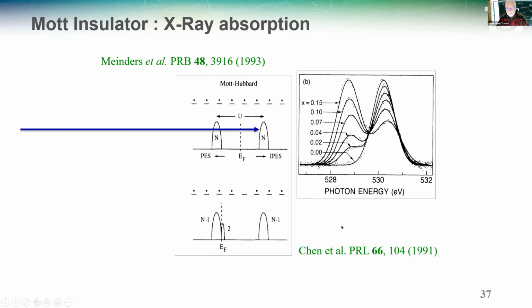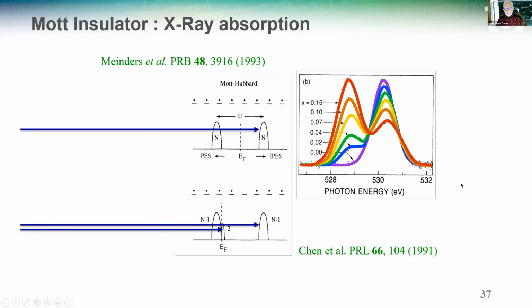So let's go back to the experiment. If I send again my high energy photon, you see that this peak has decreased in intensity. And now you have another peak that grows here. At 2% hole doping, there's a peak that grows. And now I have the cartoon. You can see that this peak is associated with these states, and this one with these states close to the Fermi level. And this goes down more slowly than the other peak goes up.